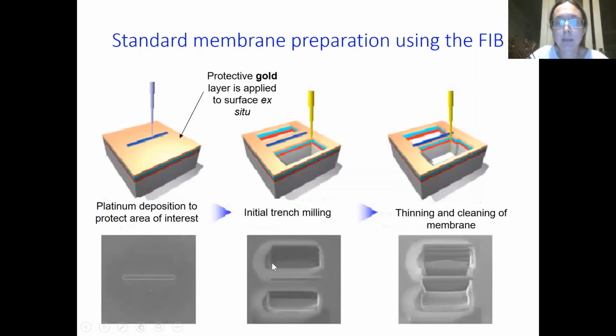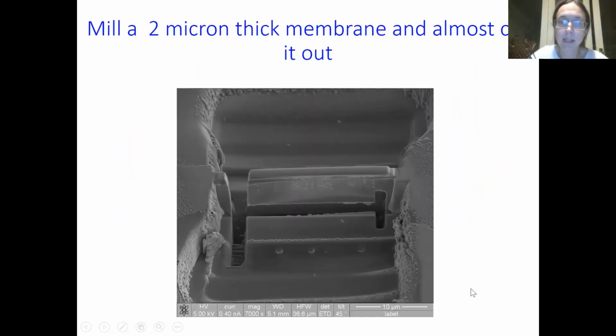And then we use the ion beam to dig 2 holes, okay? And we make the ion beam bring the sides of those holes closer and closer together until we've defined a thin membrane. Okay, so here is a thin membrane, and we've used the ion beam, and we've cut down here and along here, and this is ready to extract out of the wafer.